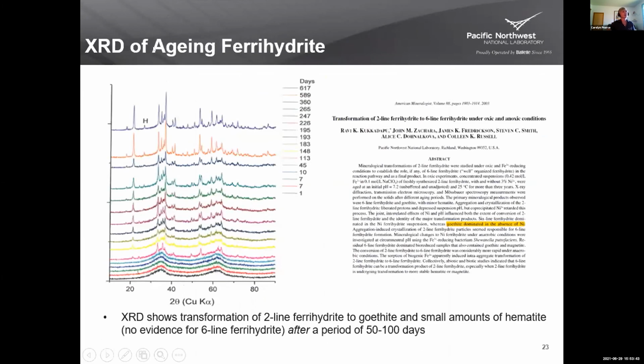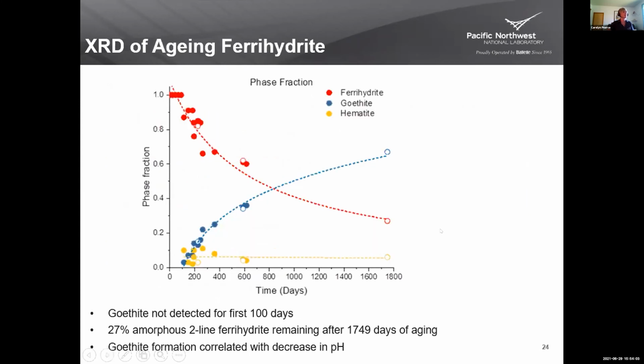So we looked at it with XRD, and showed that the first mineral phase that's formed from the transformation is goethite, which you would expect based on previous work. And then over long time periods, you see the formation of hematite, which is predicted to be the stable phase at room temperature. So these experiments have been taking place now over a period of about 4 years, and we've been looking at the phase transformation. This is aging under anaerobic conditions.